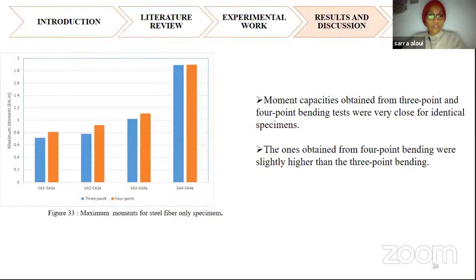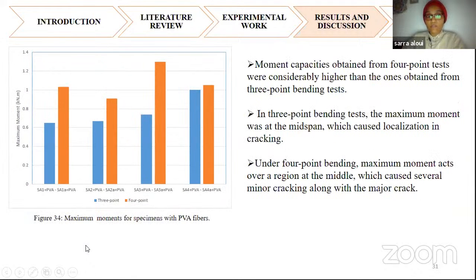Here, if we look at this graphic, the maximum moment for the steel fibers only specimen, the specimen that contains just steel fibers: if you compare the 3-point bending test and the 4-point bending test, they have very nearby results, but the specimen under the 4-point bending test still has a higher maximum moment. And for the specimen with the usage of PVA, under the 3-point and the 4-point bending tests, we can say the specimen with the 4-point bending test has the highest maximum moment compared to the other.